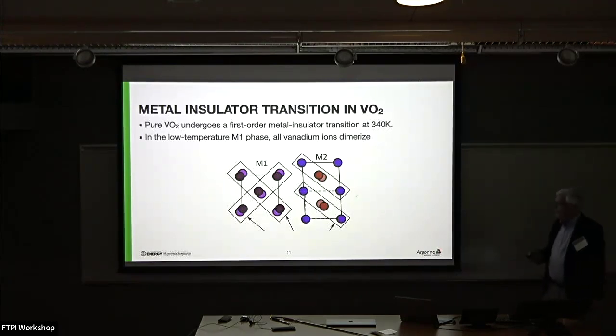But it's long been known that there is an M2 phase that you could induce by transition metal doping, where you actually remove one of the directions. In this phase, half of the chains are dimerized and half of the chains are buckled. So this was found 50 years ago. This fed into the whole debate about Mott versus Peierls for what's driving the transition.